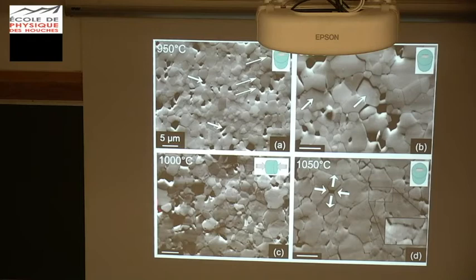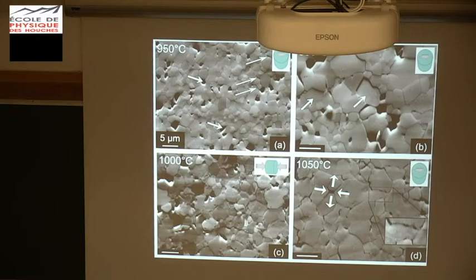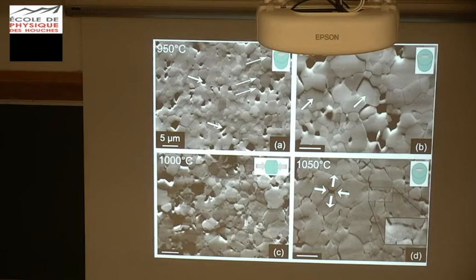Zooming in, you start to see this sort of out-of-plane displacement that we actually see everywhere. The grain boundaries remain very nice. As we increase temperature, the microstructure changes a little bit. We still have holes, gaps, voids — we're still fighting with each other about what to call them. And in one sample at 1050°C, we get something that normally we only see in textbooks: nice evidence of grain boundary sliding. Some grain boundaries show variation and very geometrical opening of the grain boundaries — and this is the first time we see that in olivine.